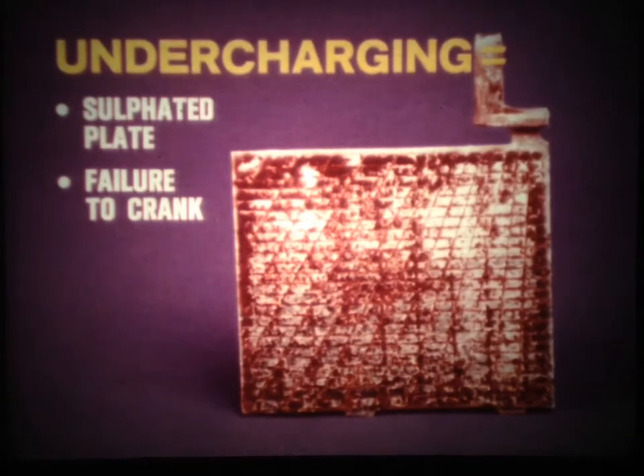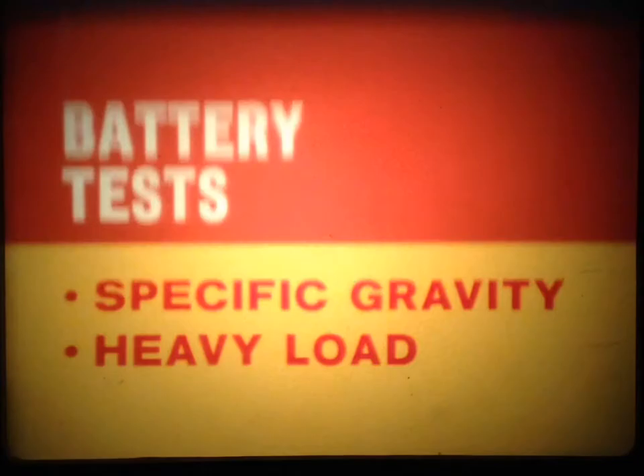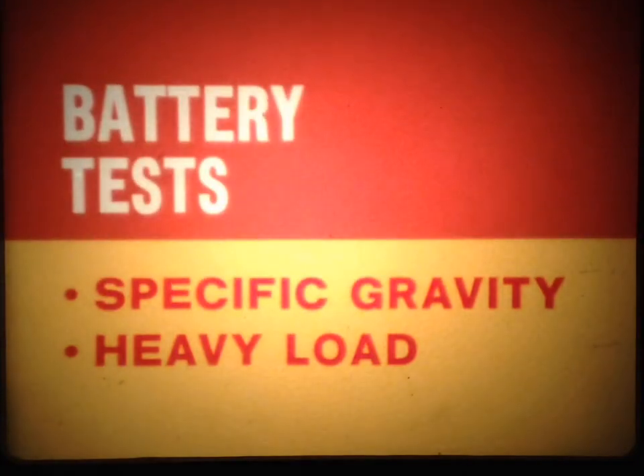Sometimes, however, a faulty charging system will not maintain the battery at full charge. This undercharging allows the sulfate on the plates to become hard and impossible to remove by proper charging. With less acid, the weak electrolyte can freeze much easier, and the undercharged battery may fail to crank the engine, especially in cold weather.